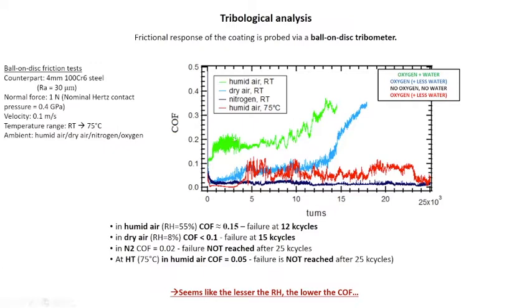But from the last test that we did, the measurement in presence of humidity but at 75 degrees Celsius, you can see that the coefficient of friction is clearly lower with respect to the measurement at room temperature. And the most important thing is that we did not reach the failure of the coating. Considering that 75 degrees Celsius is enough to induce water physisorption, but not enough to induce the oxidation of the coating, this is the first evidence that probably at room temperature, the failure is related to the physisorption of water molecules and not to the oxidation of the coating.